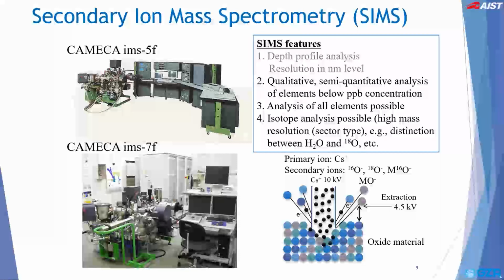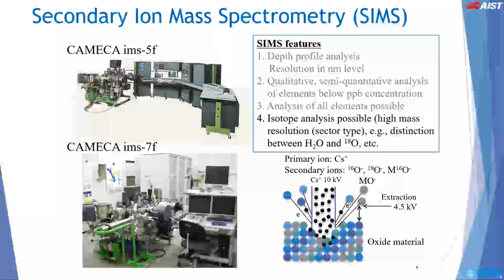Second, qualitative and semi-quantitative analysis of elements below ppb concentration is possible. For SOFCs, the presence and accumulation of contaminants, for example, trace quantities of sulfur and chromium coming from the supplied air, is detrimental to their performance. Third, analysis of all elements is possible using SIMS. Last but not least, isotope analysis is possible due to its high mass resolution. Therefore, in combination with the isotope exchange depth profiling technique, we can gain important insights into oxide ion behavior on surfaces as well as interfaces.